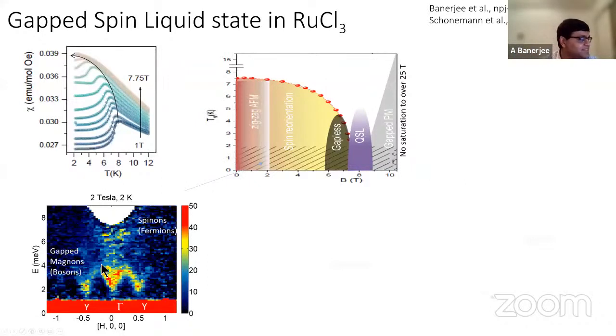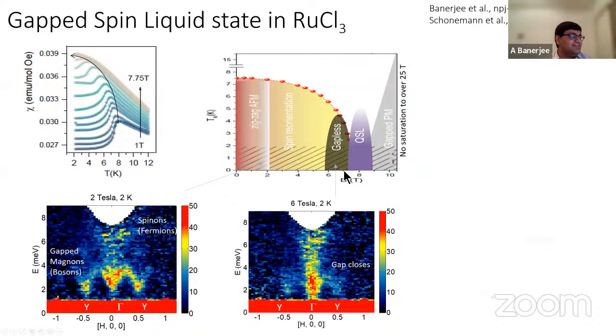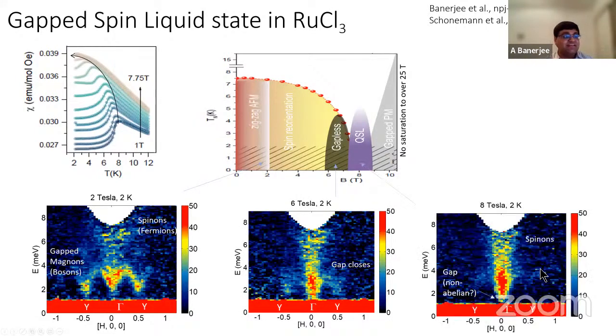If you squint your eyes, you can see what the scattering looks like. It kind of looks like this zigzag pattern. Those are the magnons, but it is also sitting on a background of spinons that we also see, which is this cloud-like spectrum. That's at low temperatures and low fields. It goes through a gapless phase. And then finally, at 8 Tesla, all the magnons disappear. You have no long-range order left in the system. You get to a pure spin liquid ground state.